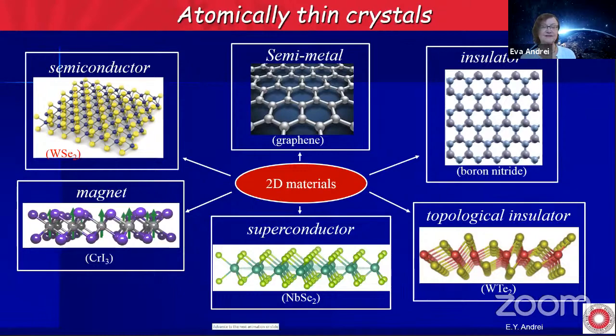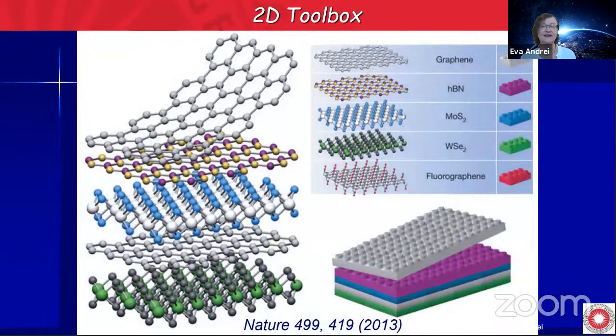So the beauty of these materials is that you can actually stack them one on top of the other. And you can just pick and choose the properties that you like to create a new material. So you can put niobium diselenide, that's a superconductor, on an insulator like boron nitride, and put on a semiconductor like molybdenum disulfide, and you can make a sandwich out of these atomically thin layers and achieve properties that you are looking for, engineer properties at will.